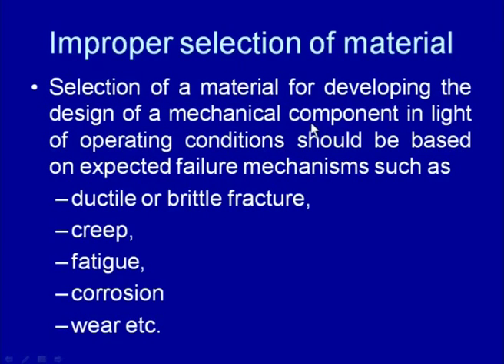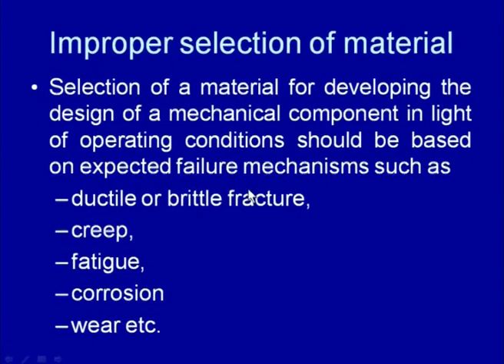Then another important factor that can lead to the failure of an engineering component or weld joint is improper selection of the material. The selection of material for developing the design of a mechanical component, in light of the operating conditions, should be based on failure mechanism. Which material should be selected for a particular component should be based on the particular failure mechanism to which it can be subjected. There will be a particular mechanism through which the component is expected to fail more than the other mechanisms, and that will be governed by the kind of service conditions to which it will be exposed. These failure mechanisms can be ductile or brittle failure, creep, fatigue, corrosion, or a variety of forms of wear like abrasion, adhesion, erosion, etc.